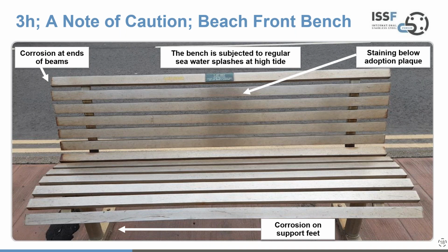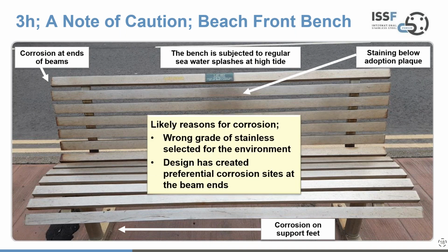But this is quite easy to explain why this particular stainless steel bench looks like it does. Probably two fundamental reasons. The wrong grade of stainless was selected for the environment. This is a seawater environment where you've got chlorides present, so you've got a higher chance of corrosion. But also the design has created a preferential set of corrosion sites at the beam ends. These are what's known as crevices, and I'll talk about crevice corrosion in a little while.